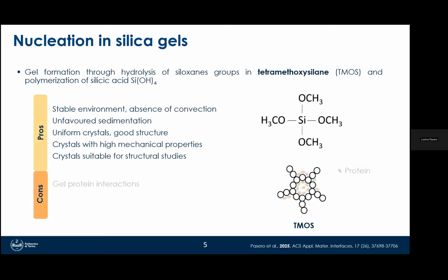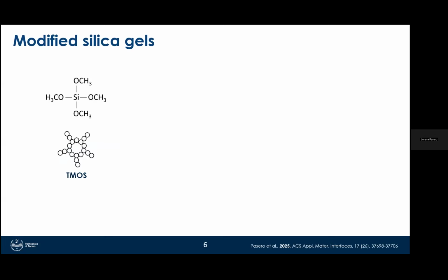However, we can face different interactions between the gel and the protein, which is the reason for the inhibition of nucleation. And it is also the reason for the high need of protein concentration, and so the high cost related to this technology. So if we hypothesize that silanol groups are responsible for inhibition, can we chemically modify the gels to reduce this effect?